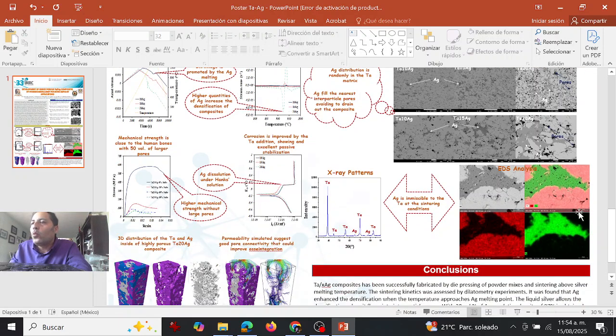In addition, the X-ray diffraction analysis and EDS analysis confirm that the silver is immiscible with the tantalum, as no silver is found inside the tantalum particles, and in the X-ray pattern we only detect the peaks that identify the tantalum and the silver alone.